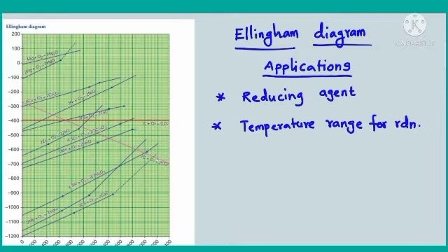For example, if a metal oxide is more stable, then the oxygen will remain with the metal. Suppose the oxide of an element used for reduction is more stable, then the oxygen from the metal oxide readily combines with the element which is used for the reduction, and in such a case that element can be an effective reducing agent for such metal oxide.